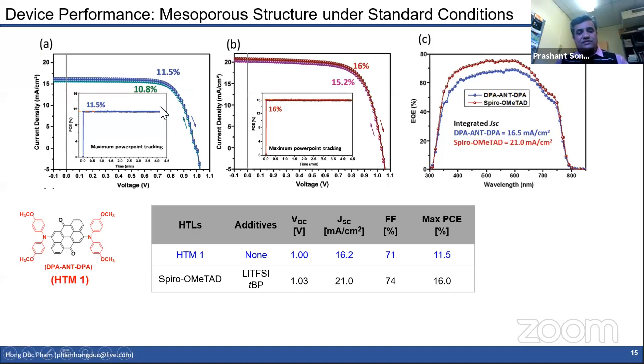This was our first device, and comparing our HTM with the Spiro devices, the highest efficiency we got was 11.5%, whereas Spiro still shows 16%, quite high. But one important aspect is that our material shows better stability than the Spiro. Looking at this, these are the data comparing with the diphenylamine and ANT, DP, ANT, and with the Spiro, like the IV curves, and that shows the current value we still get is a little less compared to the Spiro.